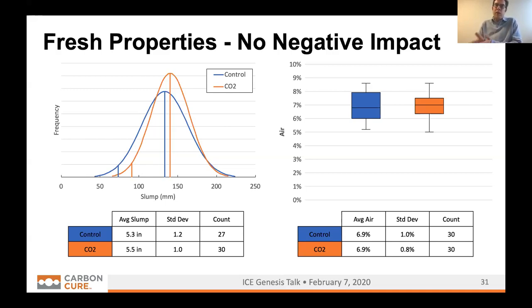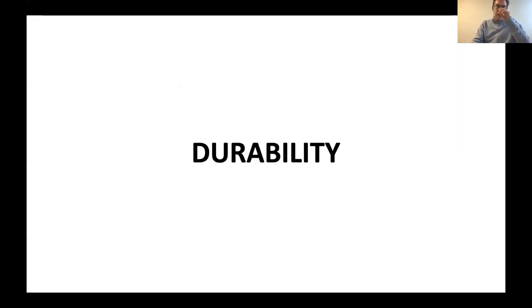And further on the right-hand side, the fresh air content, which is important, particularly in environments where concrete will be freezing and thawing. We have examples here of the producers showing that the fresh air content of the concrete is not affected by the CO2. So we're not putting bubbles of CO2 into the concrete, we're putting mineralized CO2 into the concrete, so we're not affecting the air content in any way. These concepts tie into durability.